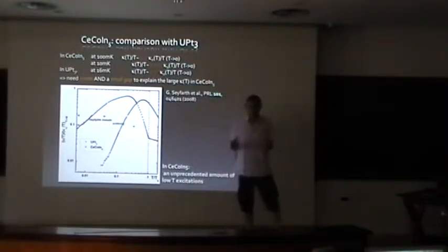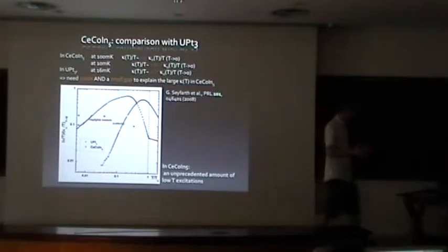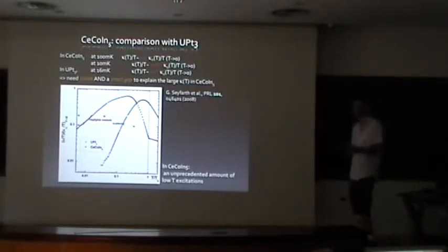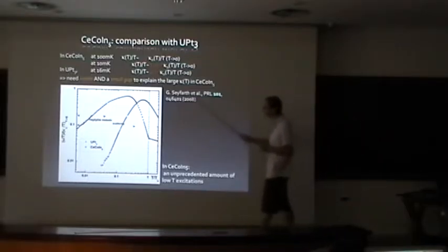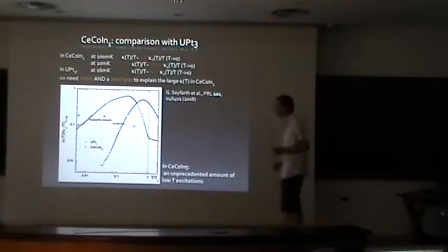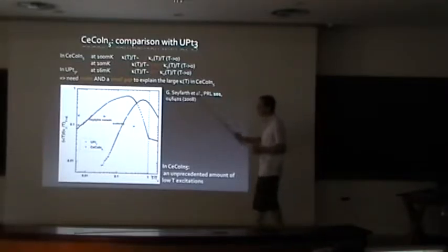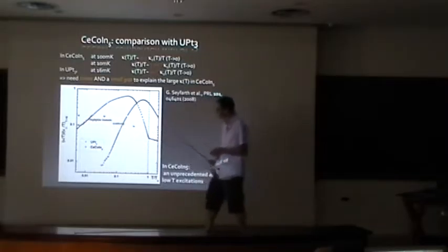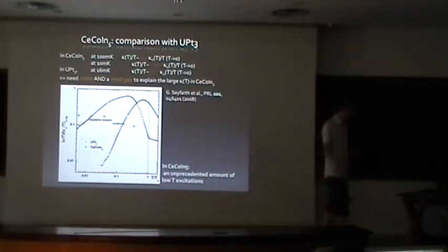So this is simply really that you have probably both a small gap and also a D-wave superconductor, which is well established in this compound. You have d_x2-y2 superconductivity. But probably you have d_x2-y2 superconductivity and also with a very small gap. So it's both multi-gap and unconventional.